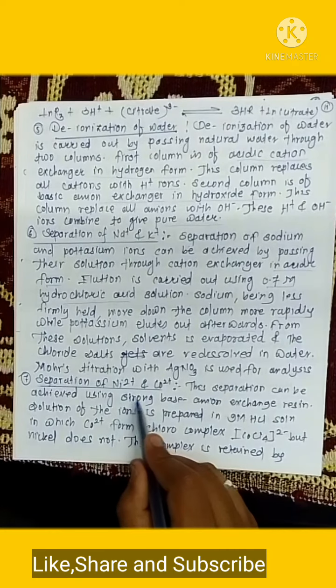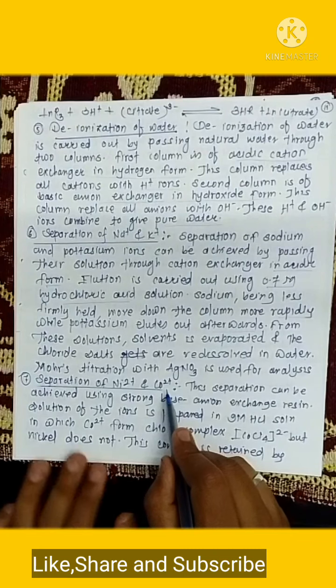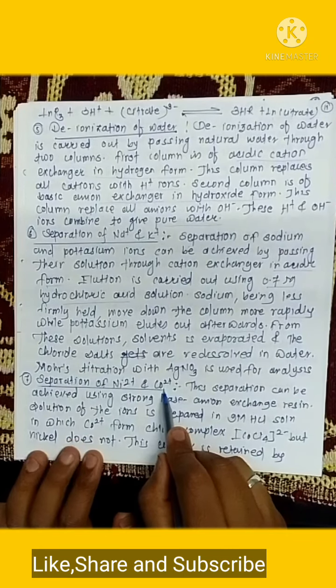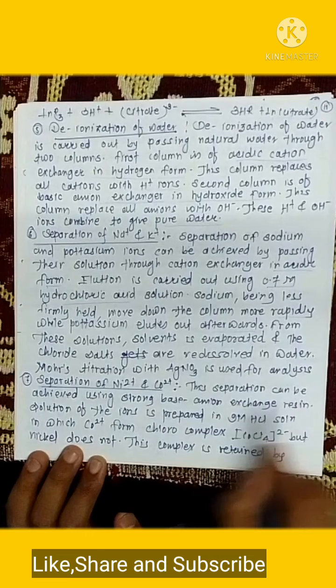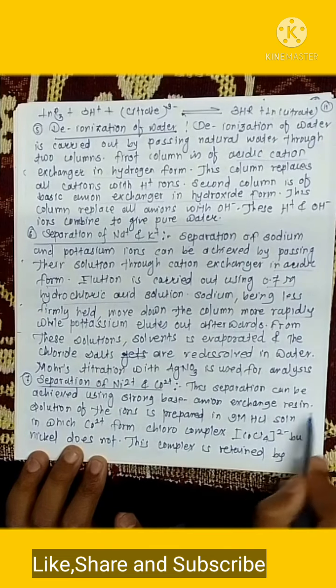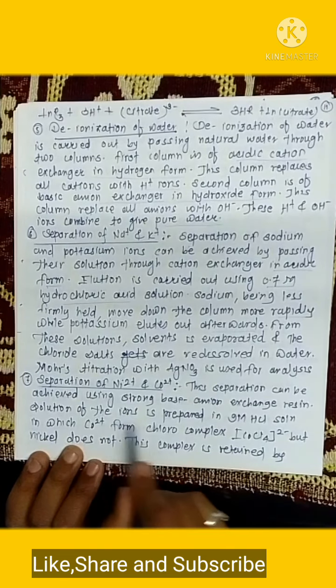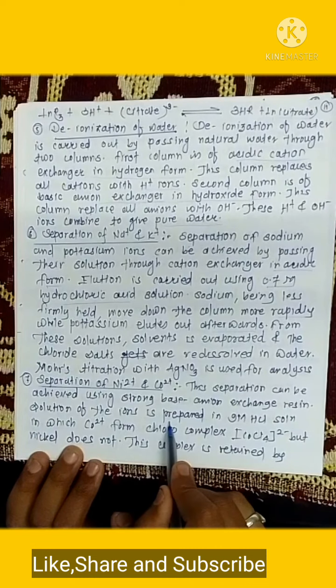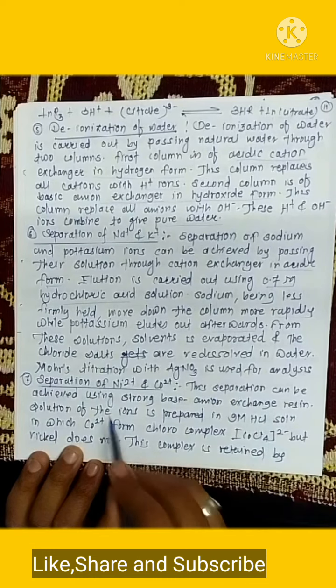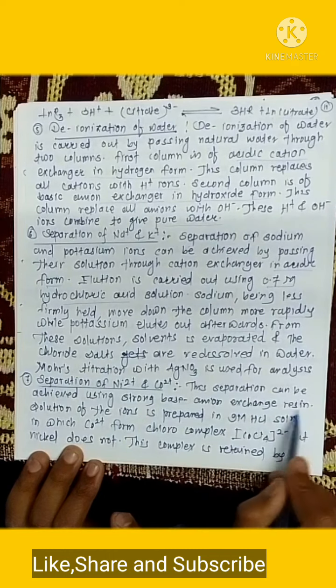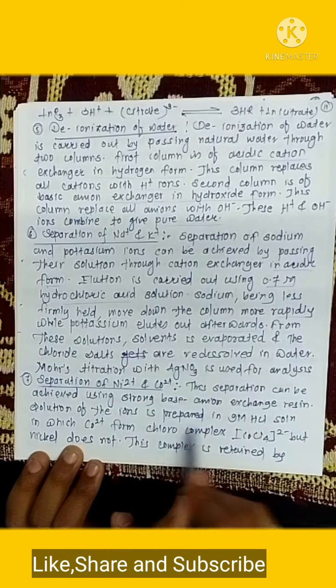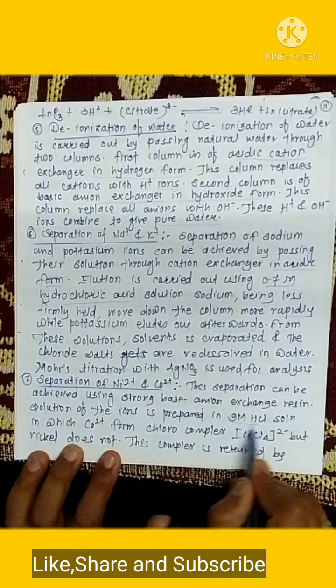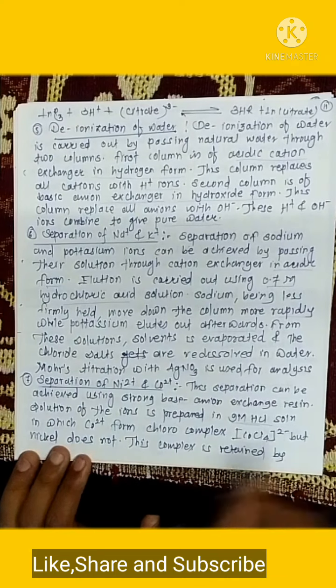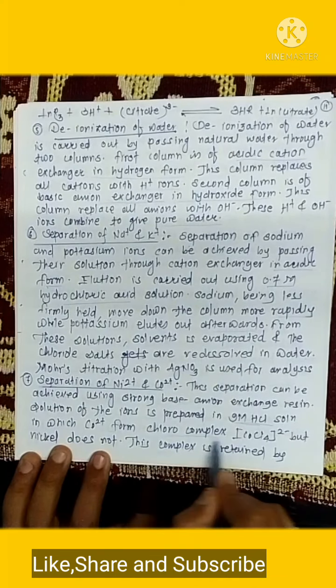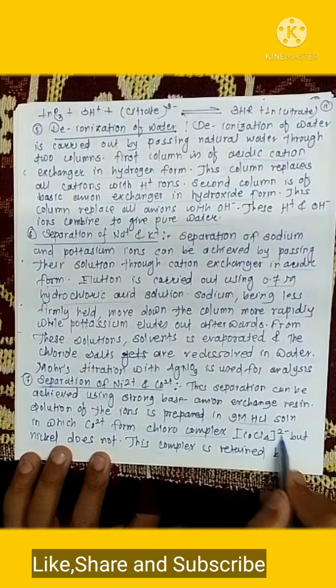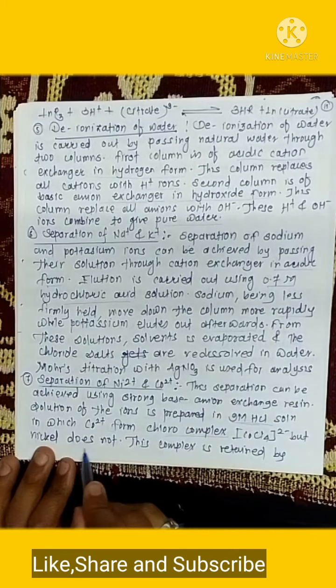Separation of Ni2+ and Co2+ can also be done with the help of the ion exchange technique. This separation can be achieved using a strong base anion exchanger resin. A solution of these ions is prepared in 9 molar HCl solution, in which cobalt 2+ forms the chloro complex, that is CoCl4 2-, but nickel does not react.